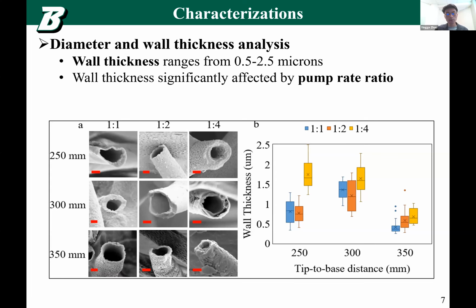Why the wall thickness matters is because we want to know if the surface pores are just surface or are they through holes. If the wall thickness is too thick, then the surface pores will not be able to penetrate into the microtube, and therefore it cannot function as capillary vessels. So we want to see if you can control the wall thickness as well. And then we found out that only the pump ratio has a significant effect on the wall thickness. The distance has no significant effect on the wall thickness.